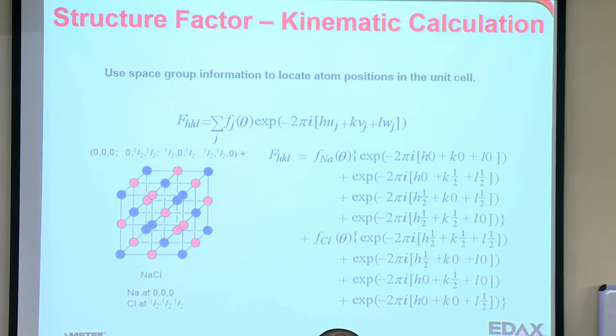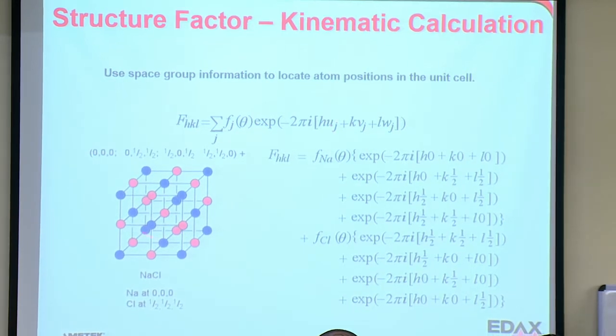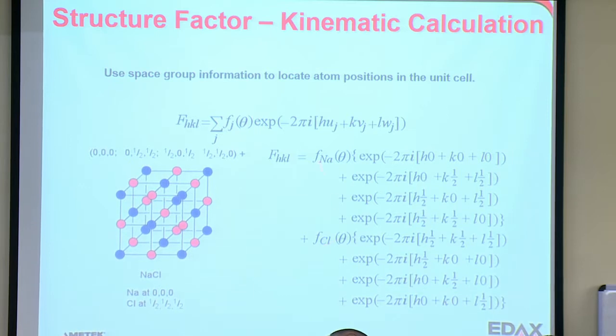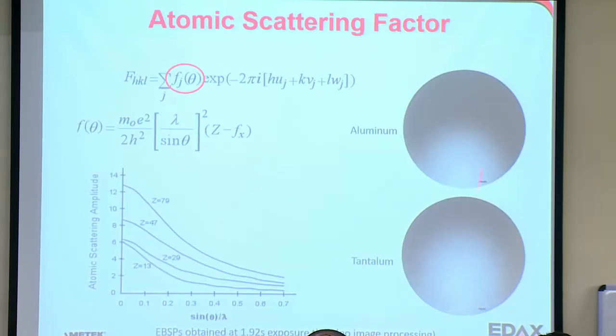So why do certain bands appear and not others? It has to do with the atomic planes, as I mentioned. We know that the intensity of the bands is a function of the structure factor. And the structure factor is calculated like this according to kinematic theory. You have an atomic scattering factor here. These, hkl, are the indices of a diffraction or crystallographic plane. The uvw, usually I use xyz, are the positions of the atoms within the unit cell. So from that you can calculate a structure factor. This is just an example for salt. And if you do that, then you can calculate the strength of these bands.